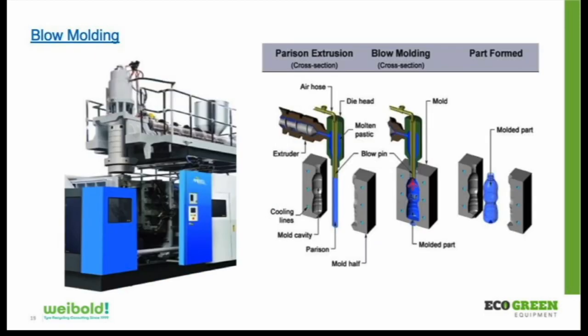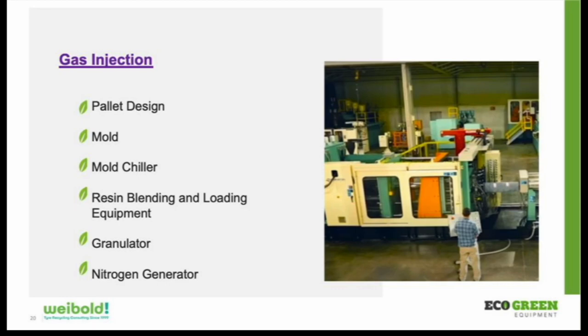On the gas assist, it's hard to see it, but you have the injection unit here, but then you have a bunch of little smaller injection units all positioned across the part. So on a pallet, a 4x4 pallet, you may have as many as 16 different injection units that are putting plastics into this part. That's important because, again, with the rubber in there, the rubber isn't totally melted. So the quicker you can get the material into the part, the better surface finish you're going to get. And there are other things you can do to improve surface finish post injection, and we'll talk about that in a minute. But the bottom line is the quicker you can get the material into the part, the better part you're going to get.